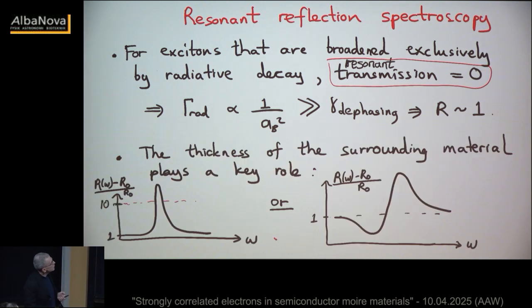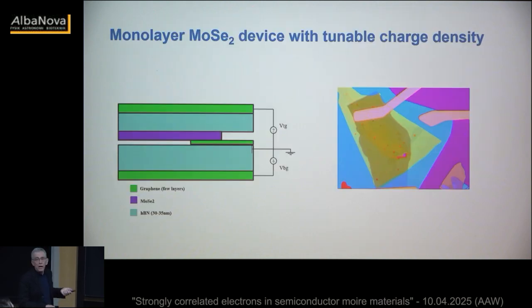Now that's not so important. What is important is what we see as we tune our white light source or laser. There is some background reflection coming from all the dielectric interfaces, like air to hBN and so on. When you hit the exciton resonance, the reflection is maximum, right? But if the background reflection is also important, and it can be given that the dielectric constants are sizable, then you'll have an interference pattern, more of a dispersive one. Right? So that's the standard scenario. Let's see how it looks in a real experiment.